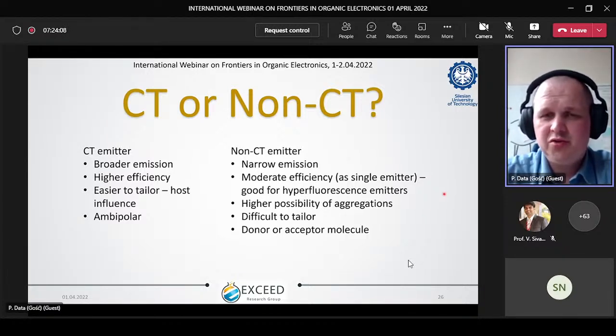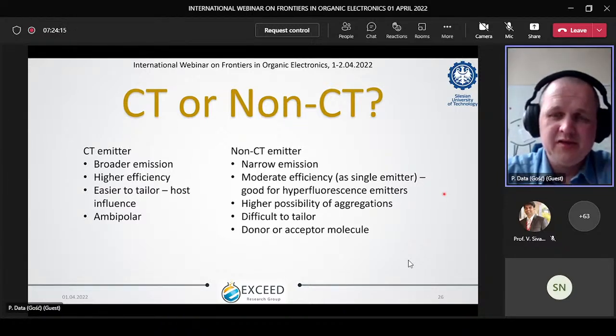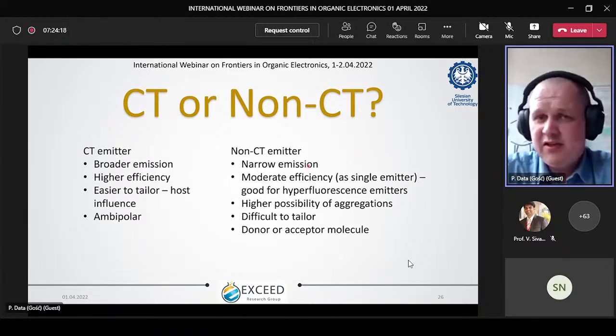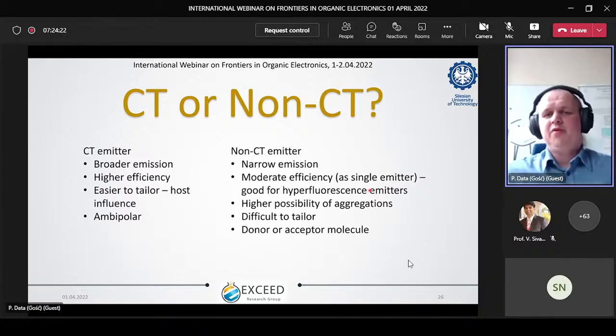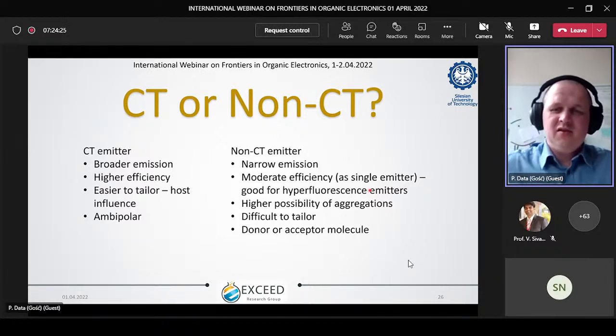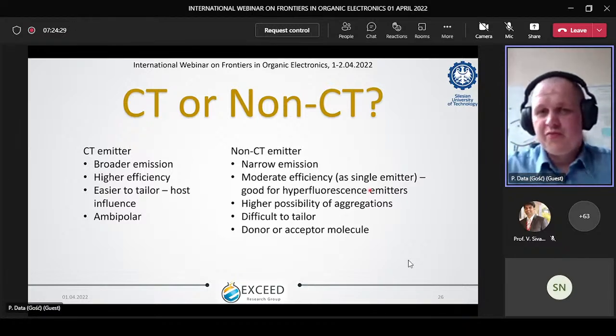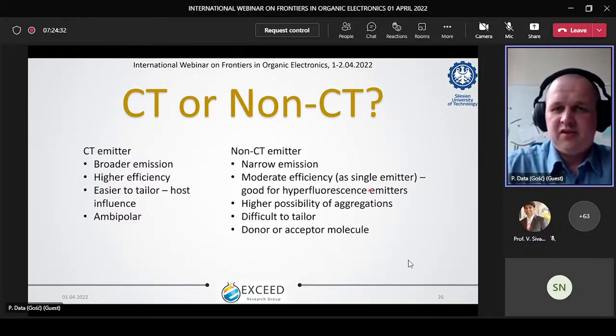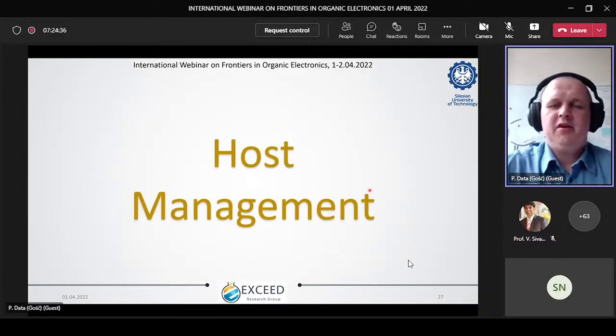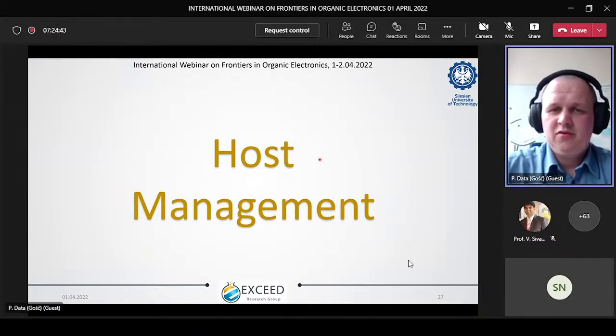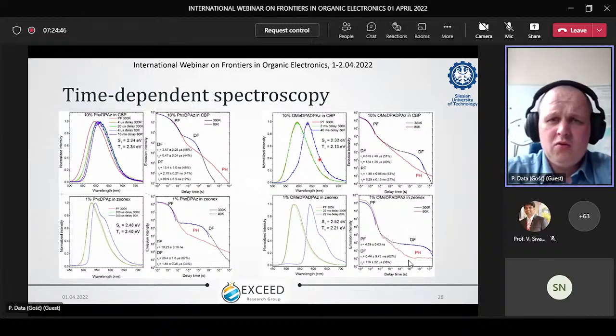Whereas with non-CT emitters, in most cases we need a proper host to use them in OLEDs. Nevertheless, most CT and also non-CT emitters you can use as hyperfluorescence emitters. So generally, it depends where you want to use them. Both of them have pros and cons. So we are now going to host management. You have your TADF emitter, and you need to know if there is a way to use this material. All the CT-based emitters, so we can say most TADF emitters, are affected by the host.